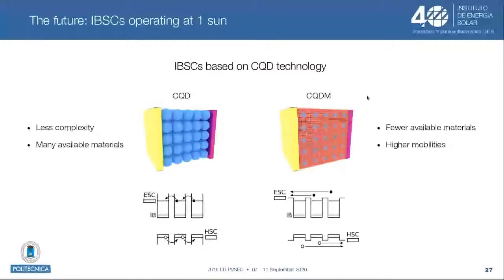The reason is sketched down here: in the CQD approach, we need to rely on hopping from dot to dot for current transport, and this tends to give very low or somewhat low mobilities, while in the CQDM approach, carrier transport takes place inside the bulk material, which can be very high, for example using a perovskite, as we commented before. Can you conclude, Inigo? Yes.